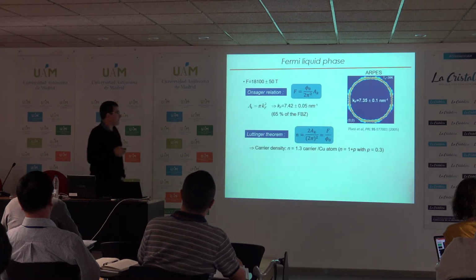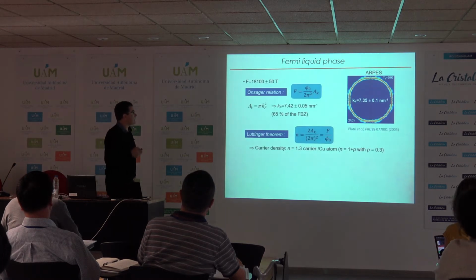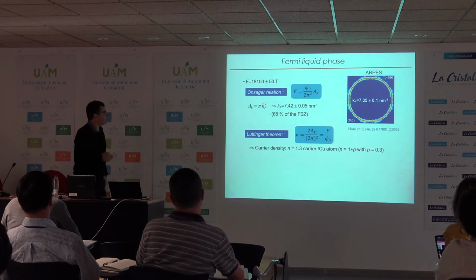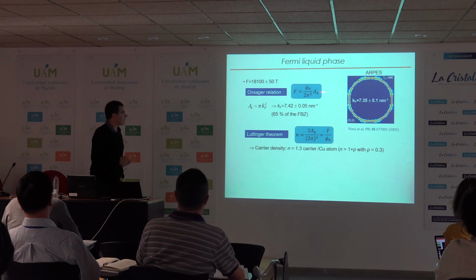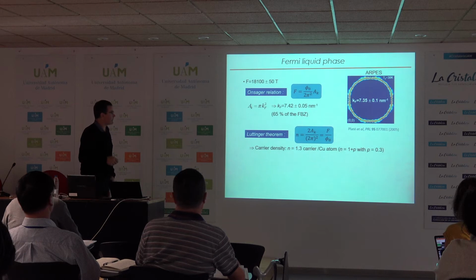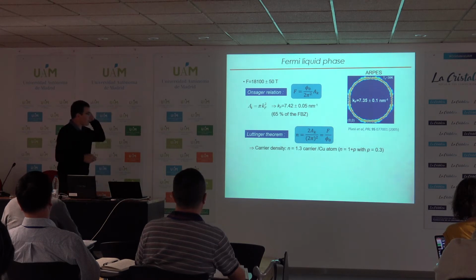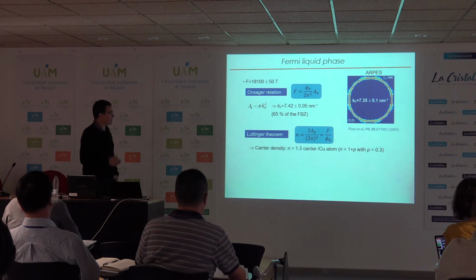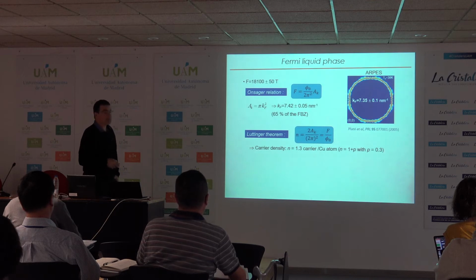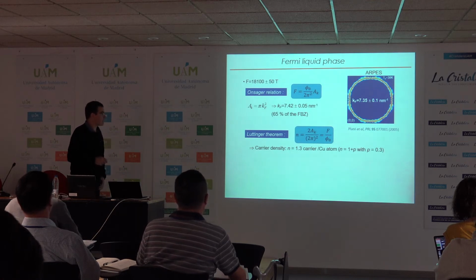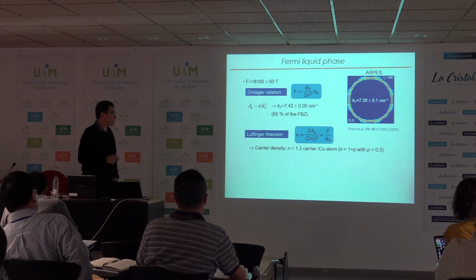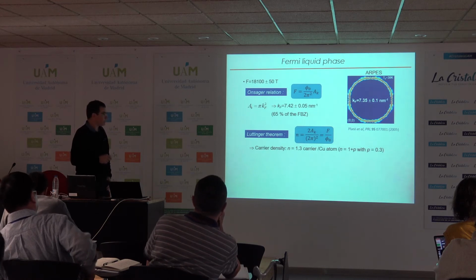So what can we say about this measurement in thallium-2201? We found a frequency of 18 kilotesla. If you apply the Onsager relation, where A_k is the surface of the cylinder, and convert it to k_F, you find a k_F of around 7.4 nanometer^-1, which is in very good agreement with what has been found by ARPES in the same compound with the same doping. This represents 65% of the Brillouin zone.